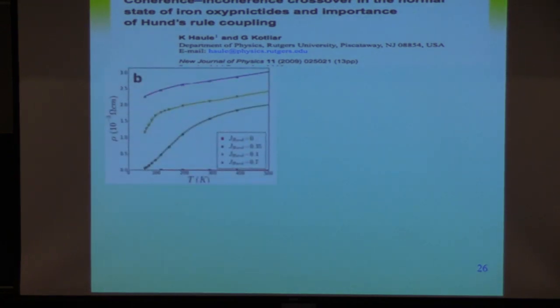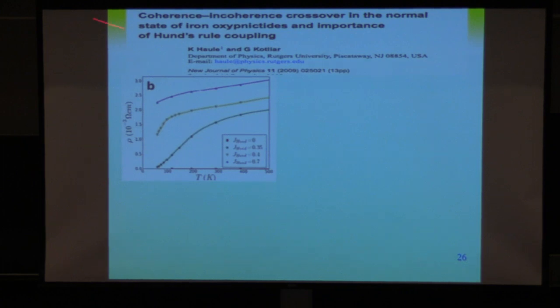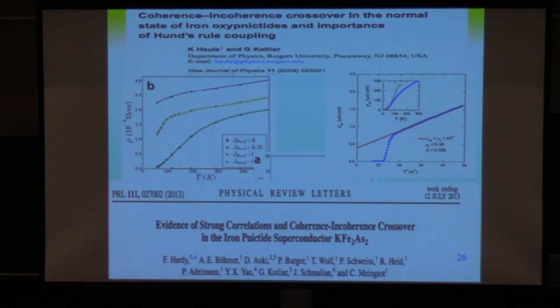The other thing that was very interesting is that we can actually vary independently in the computer the various parameters. And what we noticed is that the large enhancement of the mass was not due to Mott-Hubbard physics, like in vanadium oxide, but to a completely new mechanism, which is due to the Hund's coupling on the iron. And that's why we call these materials Hund's metals. This is the physical values of the parameters of the iron pnictides, and we discovered a crossover between a Fermi liquid at low temperatures and a very highly resistive state at high temperatures.